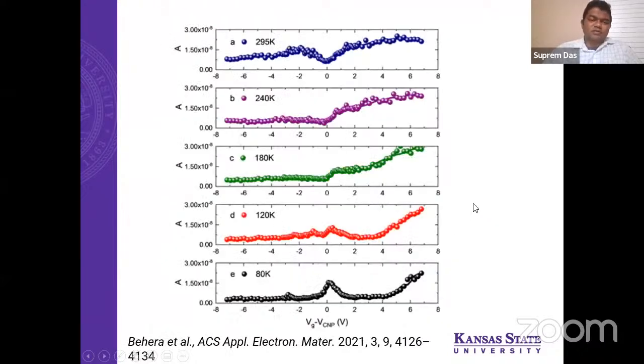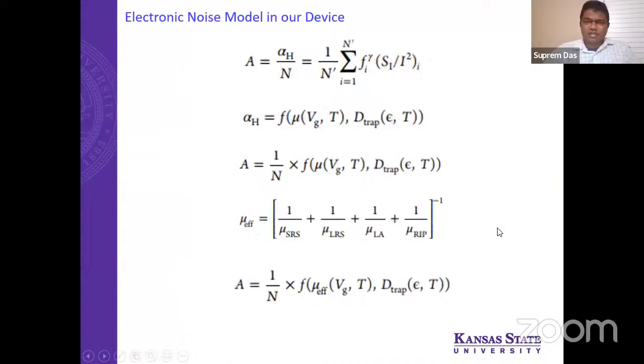So when we extract the so-called noise amplitude versus the gate voltage with different temperature, as you can see, depending on what temperature, we can vary this noise at the Dirac point from this lambda type to V type. So this is the first time we have a systematic understanding of how noise changes at the Dirac point from lambda type to V type. And that was something really, really interesting.